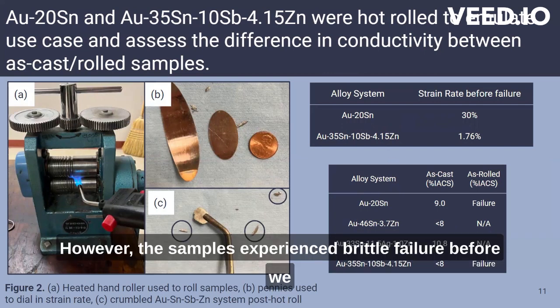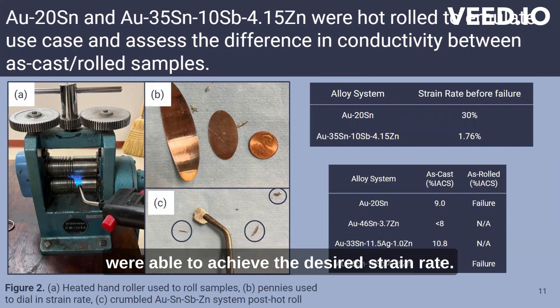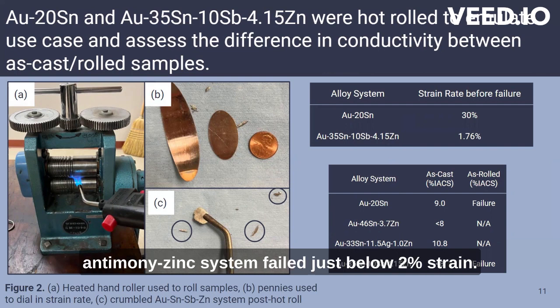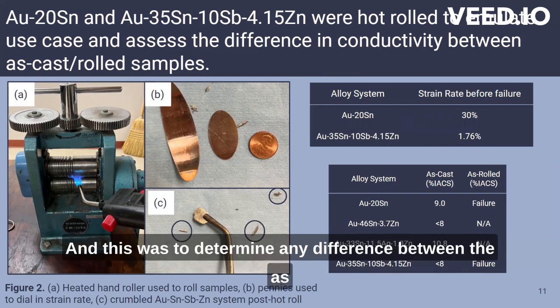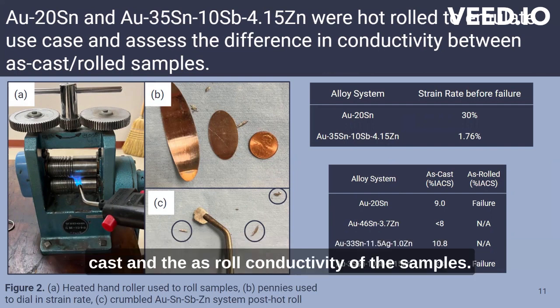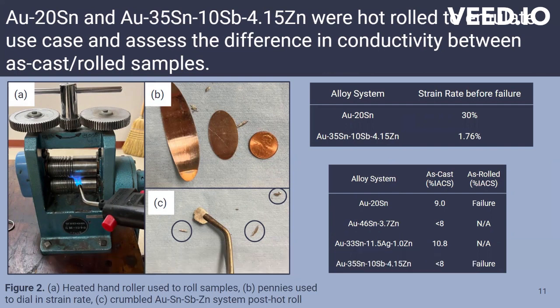However, the samples experienced brittle failure before we were able to achieve the desired strain rate. The control system failed at 30% strain, and the antimony zinc system failed just below 2% strain. And this was to determine any difference between the as cast and the as rolled conductivity of the samples.